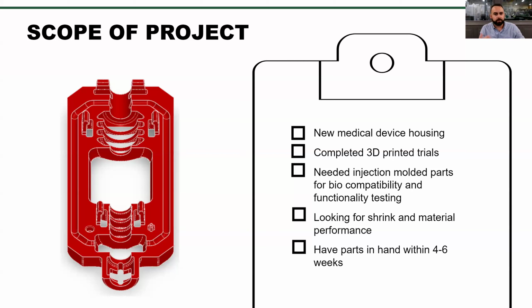They came to us with two parts. I'm going to focus on one of them, but they were basically two medical housing pieces, the top and bottom, that came together with the latch features that you see there. They already had the 3D printed part trials taken care of, but now what they needed to do was start to test the resins they were looking at and do their biocompatibility testing along with functionality testing. And they were not going to be able to do this with aluminum tooling or Proto Labs. So they were really trying to look for the shrink and the material performance with multiple different materials that we ended up molding on these.